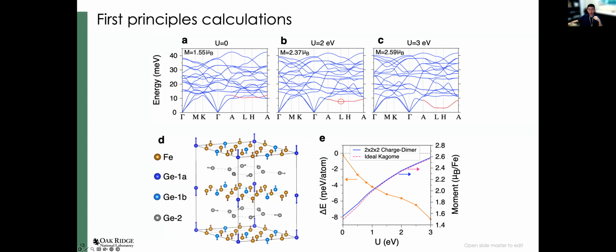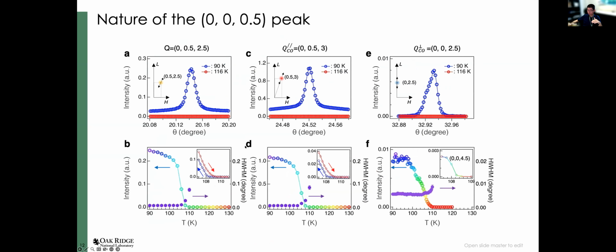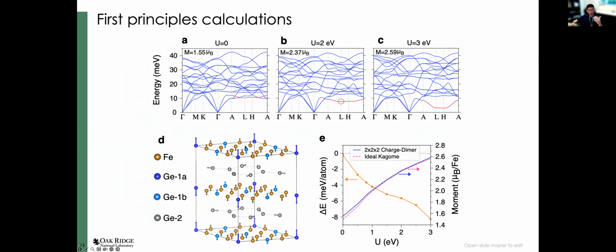And actually, if you start from a 2x2x2 superstructure and relax your lattice structure, you end up with a 2x2x2 lattice distortion. And here shows the calculated ground state energy, where the 2x2x2 charge density wave actually has a lower energy, even at U equal to 0, even though you don't clearly see a phonon softening. And if you look into the atomic distortions associated with the 2x2x2 superstructure, you find the majority of the atoms in the Kagome lattice move out of plane.